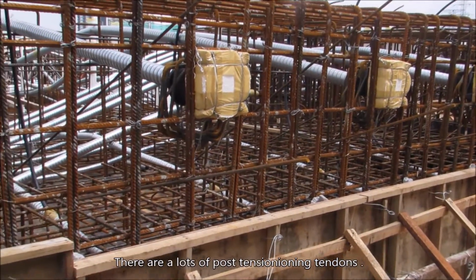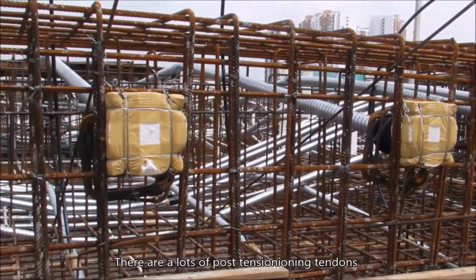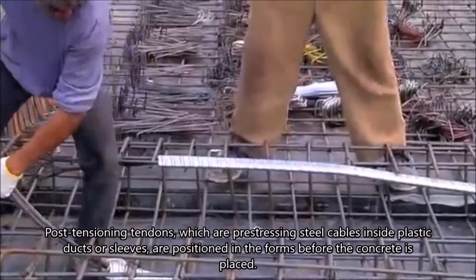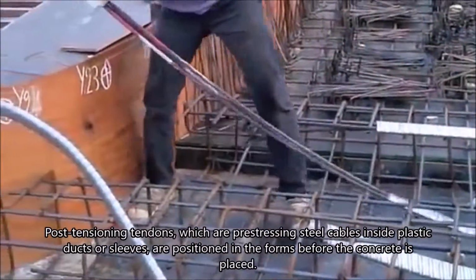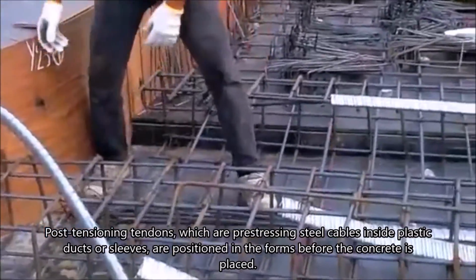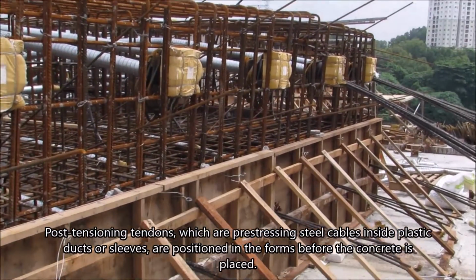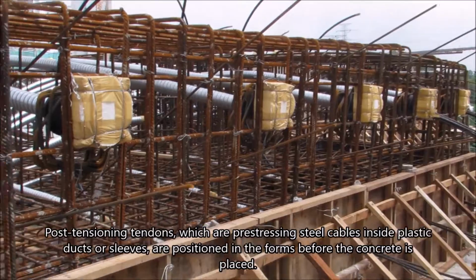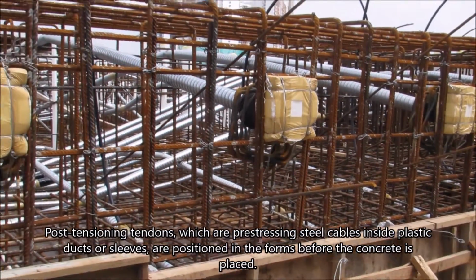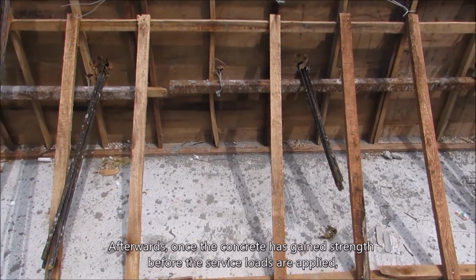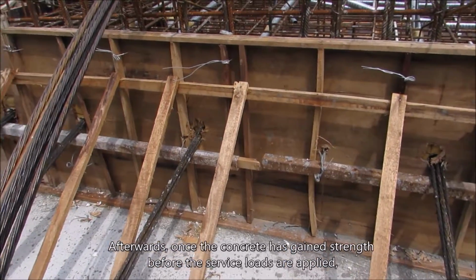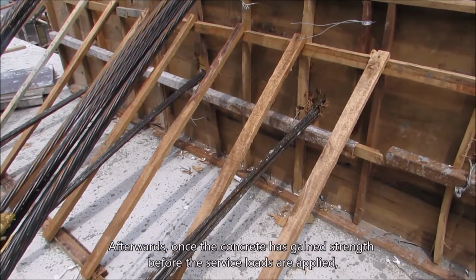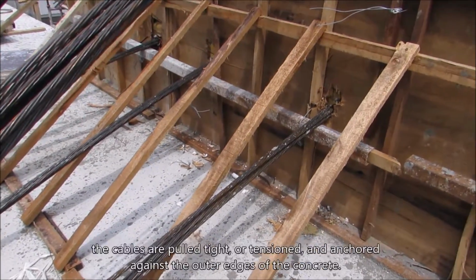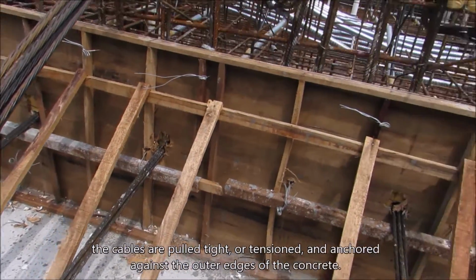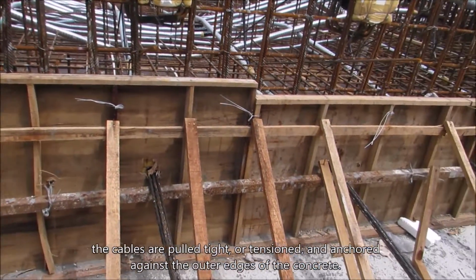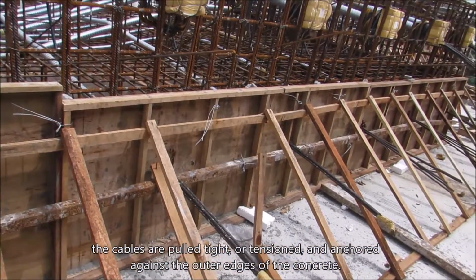There are a lot of post-tensioning tendons. Post-tensioning tendons, which are pre-stressing steel cables inside plastic ducts or sleeves, are positioned in the forms before the concrete is placed. Afterwards, once the concrete has gained strength and before the service loads are applied, the cables are pulled tight, or tensioned, and anchored against the outer edges of the concrete.